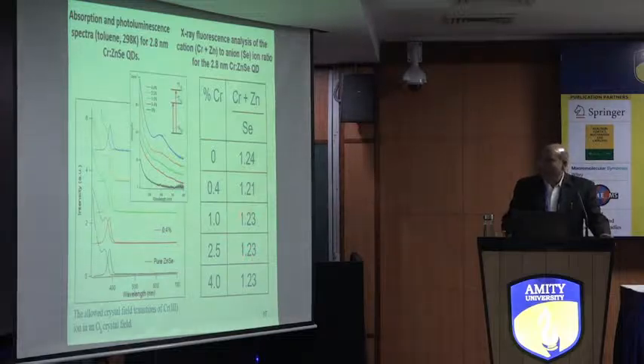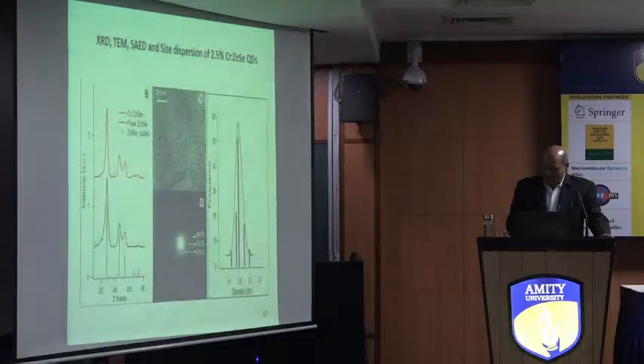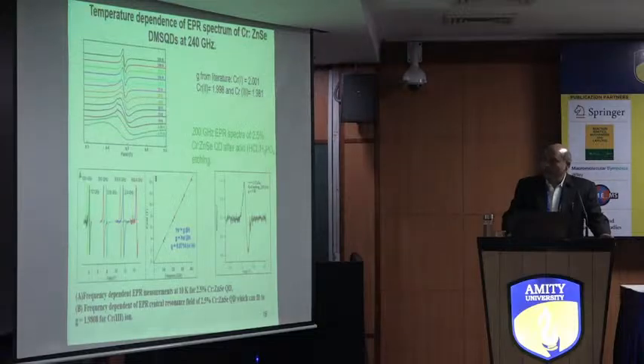Then we can say the chromium is doped inside the zinc. This is the XRD, and you can see it is showing a cubic structure. This is the dopant. Then these are the TEM images. A bunch of quantum dots are here, and the majority of the quantum dots are 2.8 nanometers. This is the EPR, from room temperature down to low temperature, 5K.